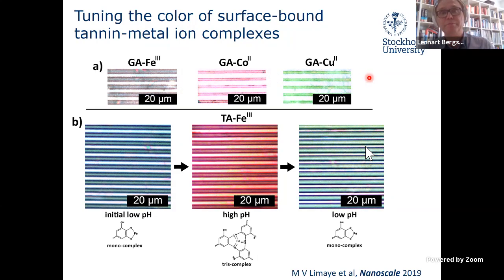What's interesting is that you can also take this one step further and go away from iron, also using cobalt and copper. Tannins are well known to form coordination complexes with a range of multivalent metal ions, forming different colors. In the case of iron, the color is also pH sensitive: at low pH it's dominated by a monocomplex, and at high pH the tris complex dominates. As you can see, these have different colors, suggesting that this kind of simple patterning approach can also be used for sensor applications.